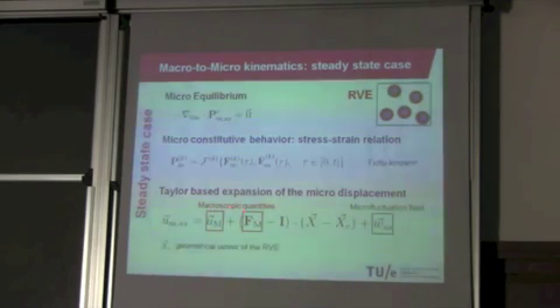And now, if we consider the displacement field within this microstructure, where the SS symbol means here that I am considering the steady state case, I have here the macroscopic part, so this is the macrohomogeneous part, which is fully defined if I know the macroscopic displacement or velocity and the macroscopic deformation. Plus, basically, everything within the microstructural response that doesn't fit on this macrohomogeneous response, which I will put in the so-called microfluctuation field.